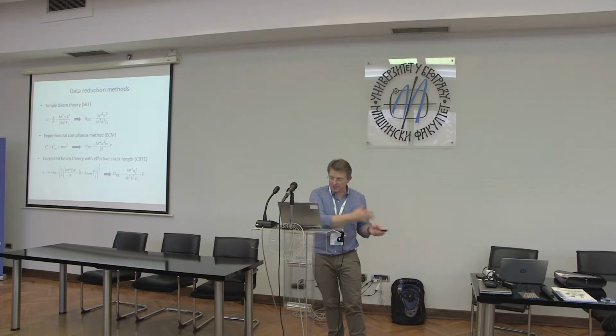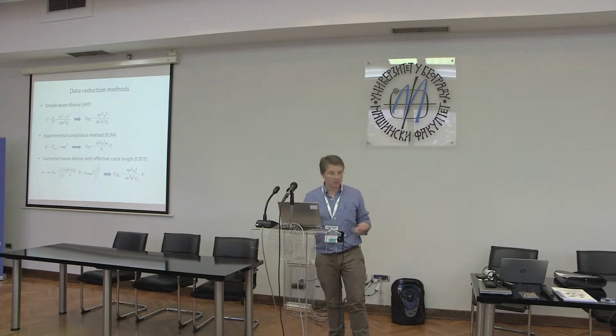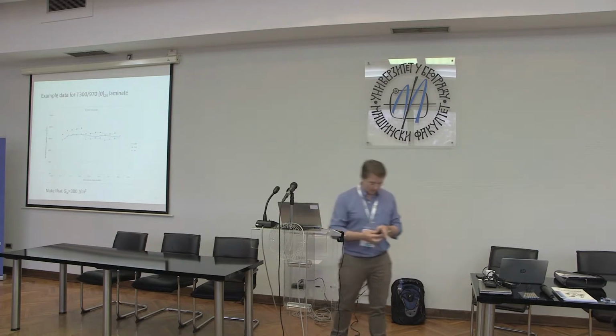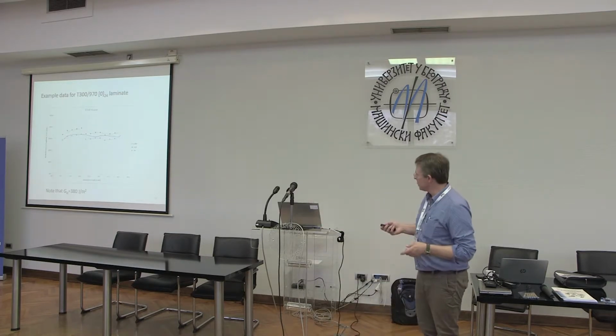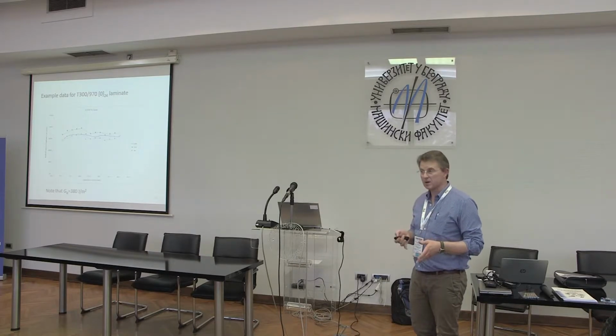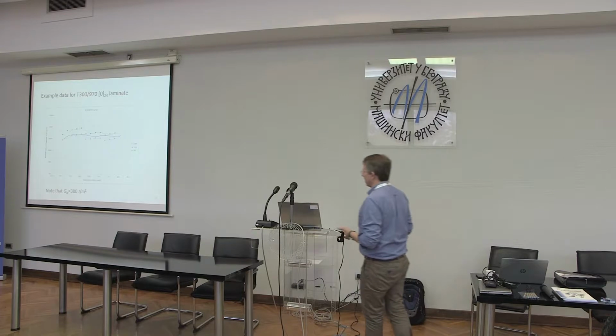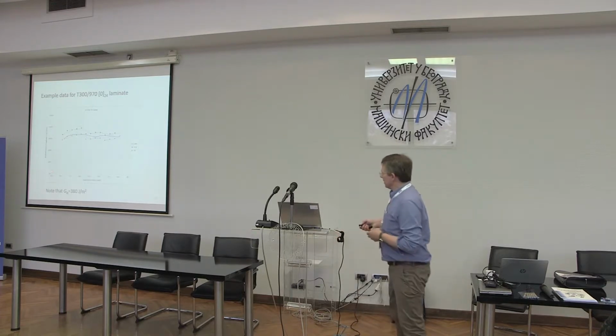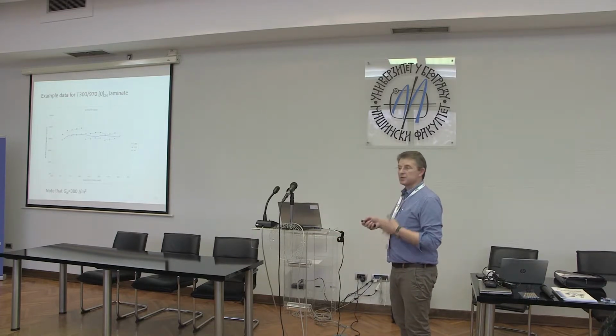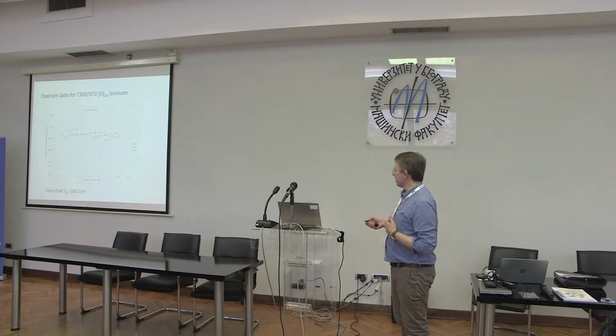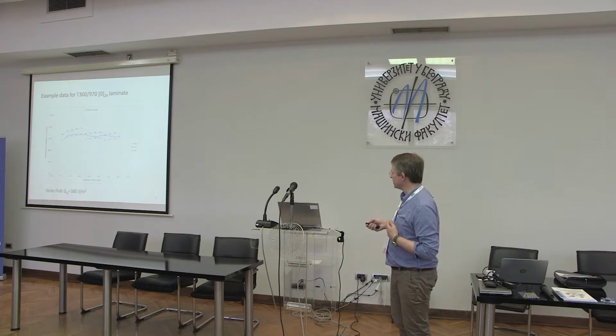Of course, ASTM have their end-notch flexure experiment. We have our ELS experiment, but both are fairly widely used. So we're able to develop these sorts of R curves, so these resistance curves. So we look at, as a crack grows, what happens to the fracture resistance, and just different ways of calculating the value. But this was our favoured approach, where we used the effective crack length values.